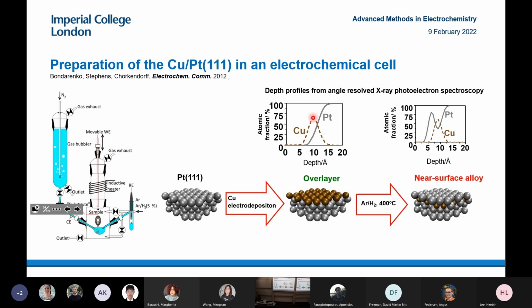So when we put the copper at the surface, we see copper is at the surface, and platinum is below. And then after annealing it in hydrogen, we see the copper is in the second surface layer. So this is exactly what we expected based on the previous ultra-high vacuum-based measurements of the surface. So now we've established a way to tailor platinum, and we think it should be a lot more inert when you have the copper in the second surface layer. So now it gave us a toolbox to play around with the reactivity of platinum.